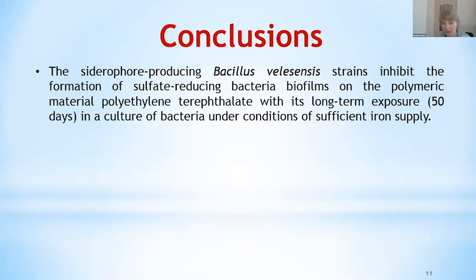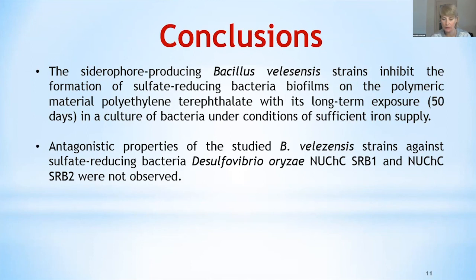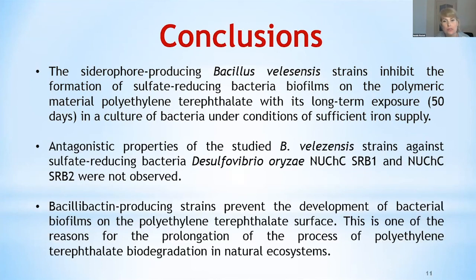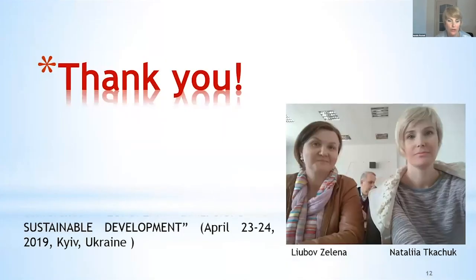Siderophore-producing Bacillus velezensis strains inhibit the formation of sulfate-reducing bacteria biofilms on the polymeric material polyethylene terephthalate with its long-term exposure, 50 days, in a culture of bacteria under conditions of sufficient iron supply. Antagonistic properties of the studied Bacillus velezensis strains against sulfate-reducing bacteria Desulfovibrio oryzae were not observed. Bacillibactin-producing strains prevent the development of bacterial biofilms on the polyethylene terephthalate surface. This is one of the reasons for the prolongation of the process of polyethylene terephthalate degradation in natural ecosystems. Thank you very much for your attention.